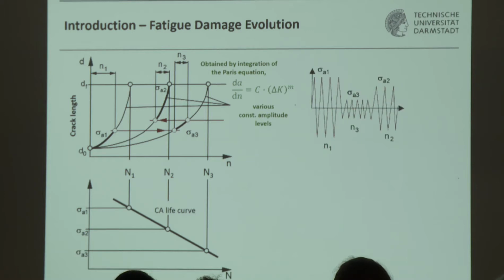and now if you are able to do these calculations, then you can have the idea to apply it to a variable amplitude loading situation and start, for example, with large amplitudes, and then you calculate the number of cycles you apply and arrive at a crack length, and maybe at that crack length you shift to a low amplitude and apply some cycles, N3. And you may want to go back to intermediate values of cycles or amplitudes, and you have another number of cycles until failure is reached.